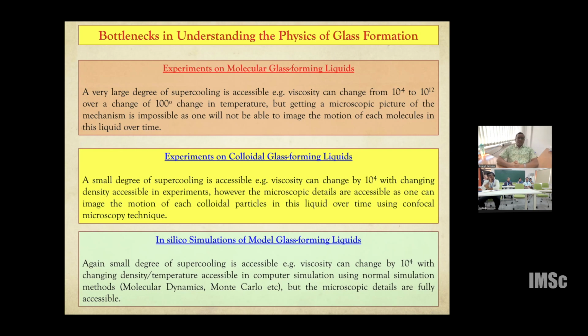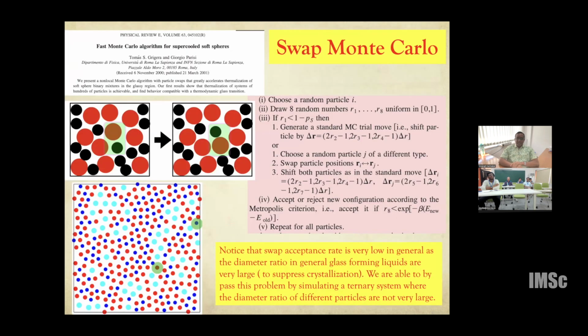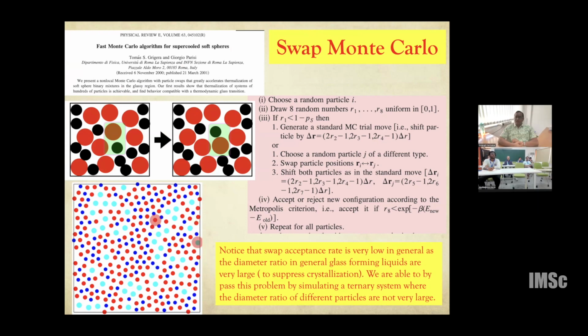But in the last 7-8 years, there has been a significant change in the various numerical techniques, and one of them is the swap Monte Carlo technique that I am going to briefly talk about. This technique was devised at least 10 years ago, or even more, I think 14 years ago, by Giorgio Parisi and his PhD student Tomas Grigera. What they proposed is that you do simple Monte Carlo simulations, but you introduce an additional step of swapping two different particles, and use the same Metropolis algorithm to accept those moves.